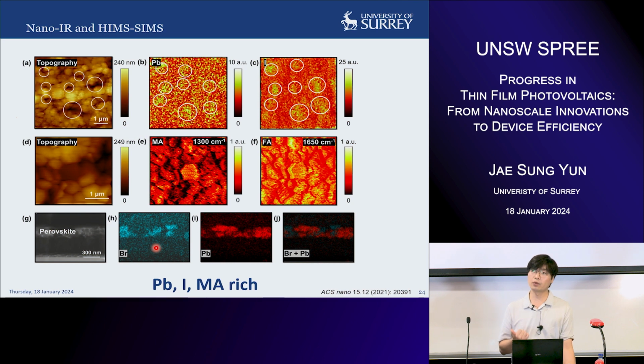Also, we can perform nano-IR and HIM SIMS in order to probe microstructural composition homogeneity. So that's the topography, and we can probe lead and iodine, and we can also probe the A site as well. These flat grains have a higher signal in lead and iodine. You can see from here. And also we have more methyl ammonium. So that's the abnormal grain in here.